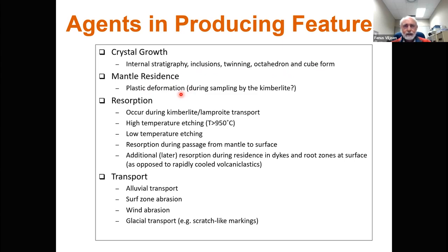If the diamond is plastically deformed and you then pick out the plastic deformation through resorption, you will end up with, for example, lamination lines. Resorption in itself, occurring at high temperature as the diamond is taken to the surface by the kimberlite, will result in a specific set of surface textures. And if we have comparatively lower temperature resorption, you'll see another set of surface textures. Resorption during passage from mantle to surface will obviously affect the diamonds and give us further surface textures.